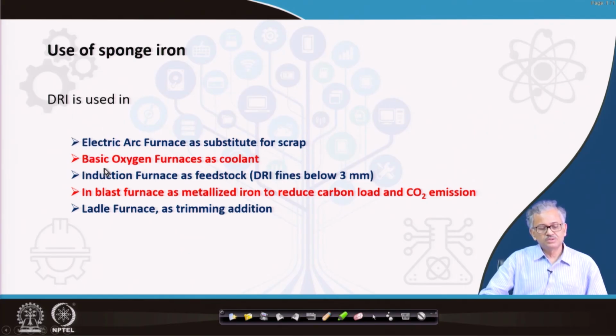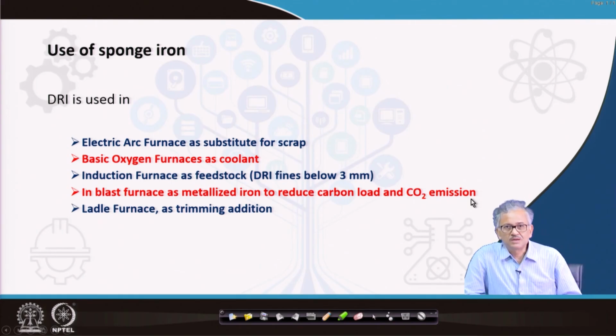Use of sponge iron: you can use it in the electric arc furnace as a substitute for the scrap. You can use it in the basic oxygen furnace as coolant, in the induction furnace as a feedstock, and DRI less than 3 millimeter, very fine DRI, you can use in the induction furnace. In the blast furnace as metallized iron to reduce the carbon load and the CO2 emission.